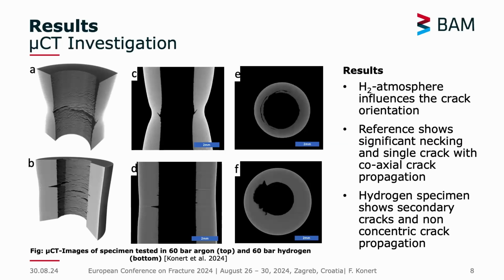And just some first insights into how such a hollow specimen behaves if we test it under argon, in the upper part of the image, and under hydrogen, the lower three images of the main image. So in argon, you just have a clear reduction of area, a clear necking, and the 45-degree angle of the fracture or of the crack in the specimen.